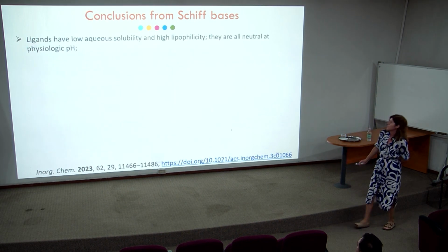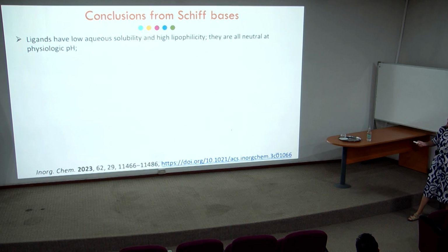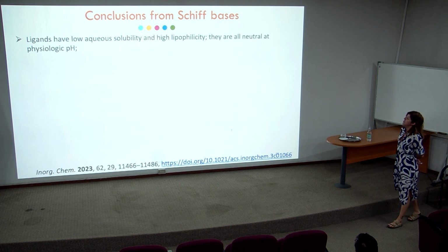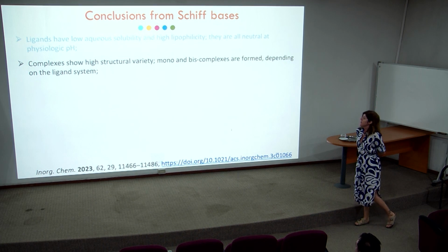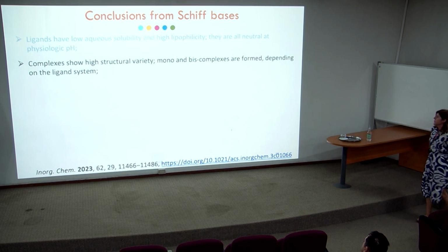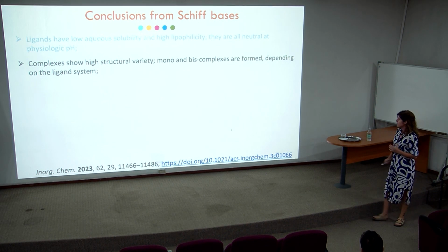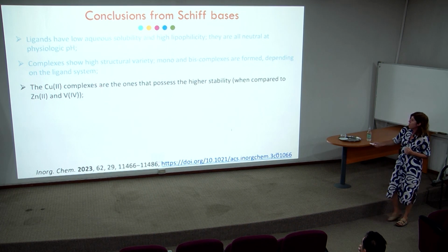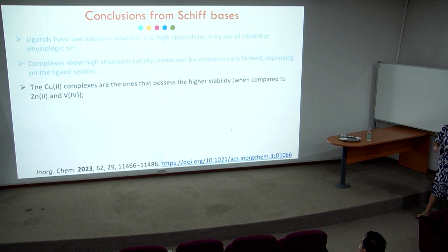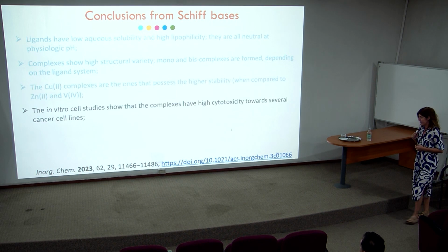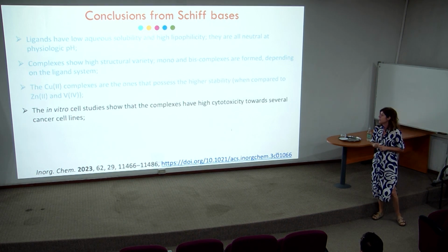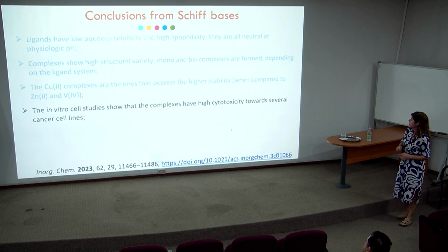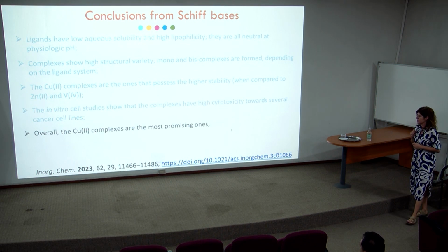So to conclude from this part, these ligands have low aqueous solubility and high lipophilicity, being again neutral. The complexes show high structural variety. We could see in the speciation the 1-to-1 and 1-to-2 metal complexes. The copper are more stable than the zinc and also the vanadium because we have data on that also. And the in vitro cell studies show that the complexes have high cytotoxicity towards several cancer cell lines. And the copper complexes are the most